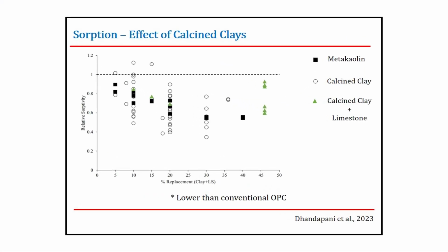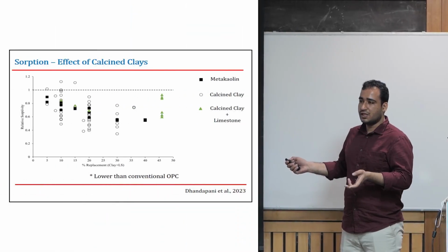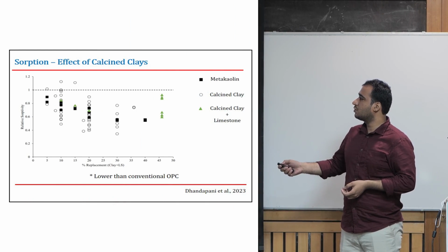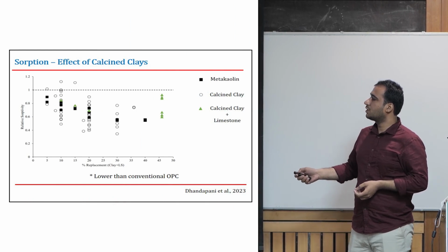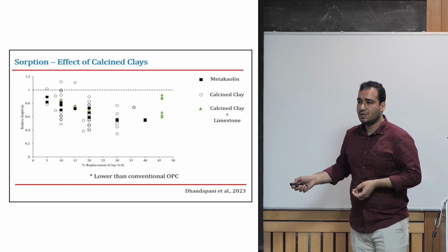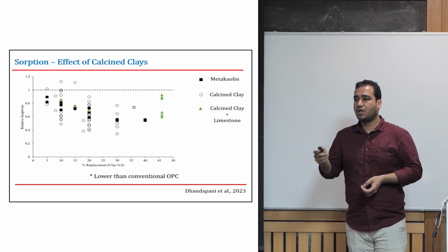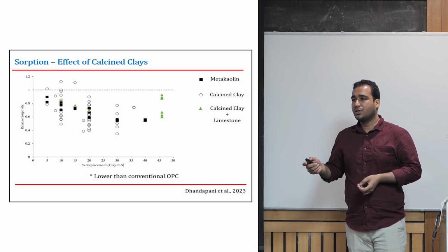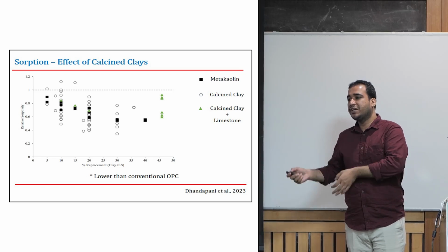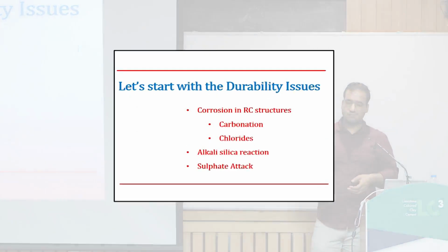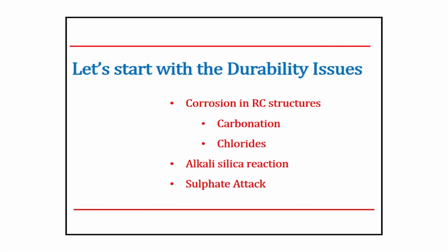This is compiled literature from Dhandapani et al. from 2023. It's a RILEM paper, a review of the durability issues with calcined clays, and you can see that when we consider different metakaolin blends, or, say, calcined clay individually or a combination of calcined clay and limestone, we always end up with lower sorption compared to the OPC system. That's because we are refining the pores. Our pore size distribution is changing. The porosity may be higher, but our refinement is so good that the ingress of water itself is reduced.